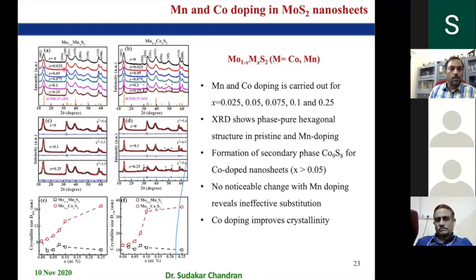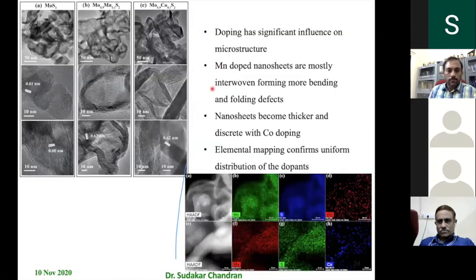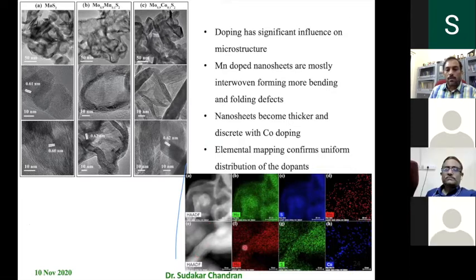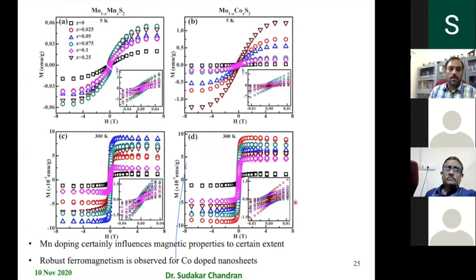in both the cases. Manganese doesn't show much variation either in the XRD or Raman studies, whereas in the cobalt-doped one, certainly at very high concentrations, you happen to see secondary phases like Co9S8 segregating. Doping also influences the layer thickness, the number of layers you have in the nanosheets, and the crystallite size and so on. So in spite of that, of course, what we see is the doping is very uniform. When we did the EDS mapping on the sheets, they seem to be uniform. And of course, there is no specific segregation we found, except in the high concentration, more than